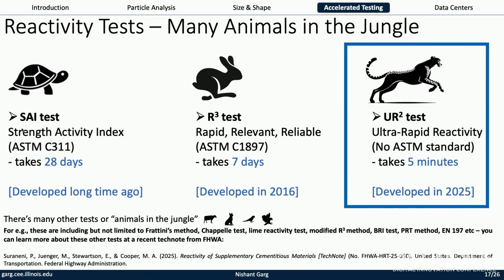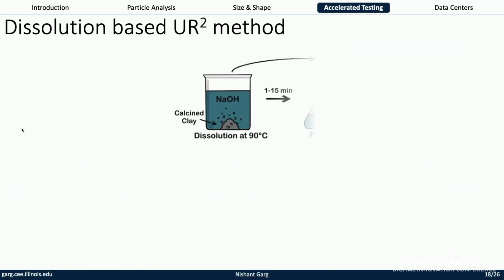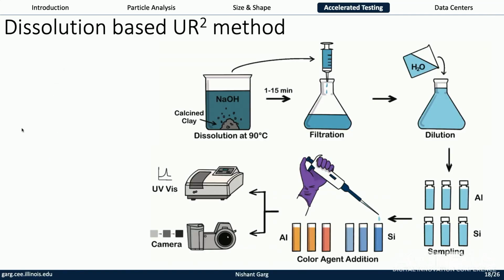But really, I want to talk briefly about the newer test that we have. Essentially, we came up with this idea that if something doesn't dissolve, it's not reactive. And then it's a question of what are the right conditions at which you should dissolve it. So figure out the right amount of NaOH concentration and the temperature. And when you dissolve it, you can get the right concentrations, which then map to long-term reactivity.